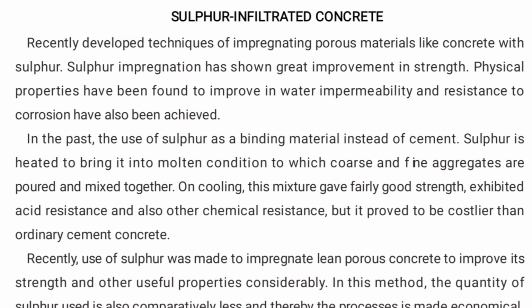In the past, sulphur was used as a binding material instead of cement. Sulphur is heated to bring it into molten condition, to which coarse and fine aggregates are poured and mixed together. On cooling, this mixture gave fairly good strength and exhibited acid resistance and other chemical resistance. Recently, sulphur was used to impregnate lean porous concrete to improve its strength and other useful properties considerably.